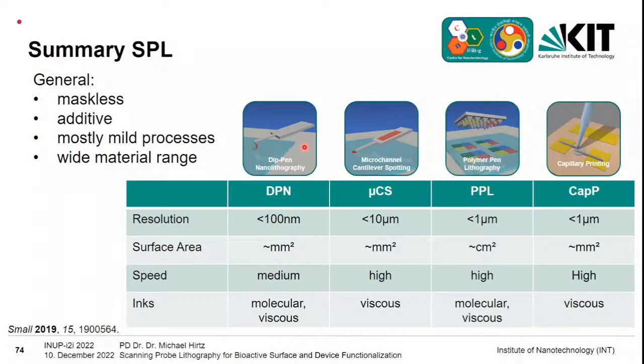Yeah. For the smallest sizes, there are two different things. One thing is what we can regulate from the tip. This is really very precise. This is basically what you can do in an AFM, so you could go even into sub-nanometer to measure. And you can address as well in this nanometer, even maybe below nanometer scale, for the registration, for which part on the substrate you can apply to.